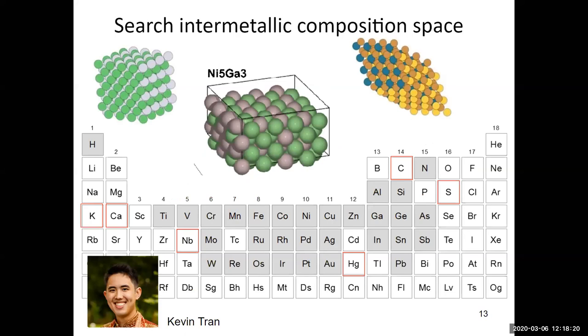Okay, so I asked my first PhD student, Kevin, to start with the database from the Materials Project and find all of the stable bulk inorganic materials from all of these elements in gray. And we've also added carbides and sulfides and some other materials since then. This is one class of materials, ordered intermetallics. In catalysis, you can also have solid solutions, usually when it's not quite as equimolar, more like 90% one, 10% the other. If these things are stable enough, there are people who really like doing synthesis of these materials. And so you can ask someone to actually go and make this specific nickel-gallium intermetallic. It's a very nice space of compounds to play around with.